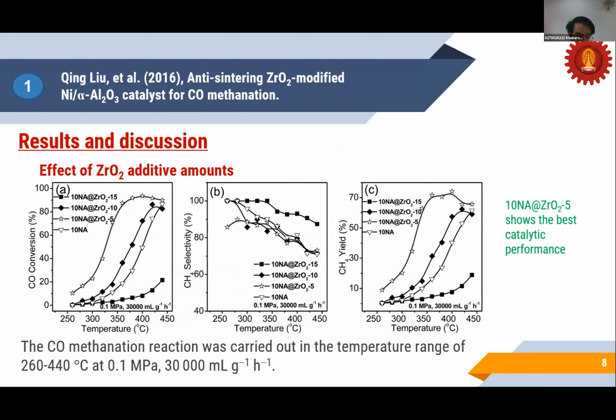Discussion: effect of zirconium oxide additive amount. The CO methanation reaction was carried out in the following condition, and the results are shown in figure A to C. It can be seen that the addition of zirconium oxide considerably improved the catalytic activity, and 10NA@ZrO2-5 shows the best catalytic performance and methane yield. It could be pointed out that the order of methane selectivity of the different catalysts is opposite with their order of CO conversion, indicating the side reaction can also be significantly enhanced in the presence of the more active catalyst. So only the proper amount of zirconium oxide can remarkably enhance the CO methanation, and the excess zirconium oxide had the adverse effect on it due to the coverage of the active site.